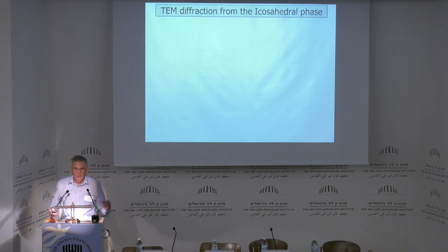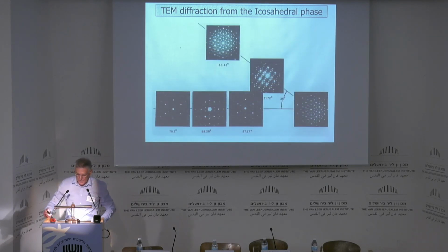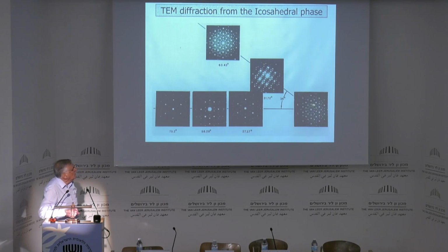Of course, in the electron microscope, you can rotate the sample, you can turn it, so you can reach different orientations. And this is what I did, and received all these diffraction patterns. So here is the fivefold. When I went so many degrees in this direction, I have twofold and fivefold again, and the distance between this and this is 63 degrees, and so on, and 5, 3, 2, 3 again.